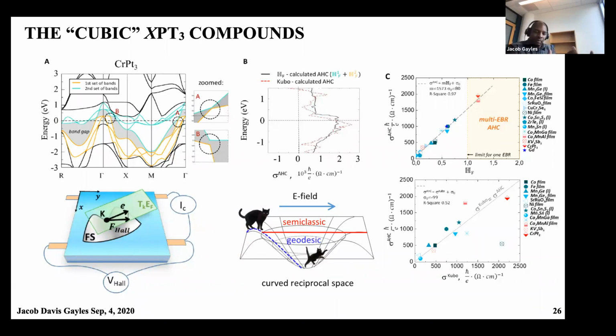so we map the Fermi surface, each point on the Fermi surface, but it's also connected to the points around it. So do you have an elliptic point? Do you have a spherical point? Do you have a hyperbolic point? And things that are hyperbolic would give rise to things that are like anomalous Hall effect in behavior.